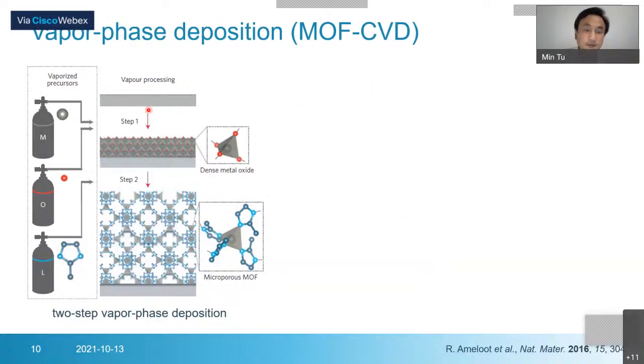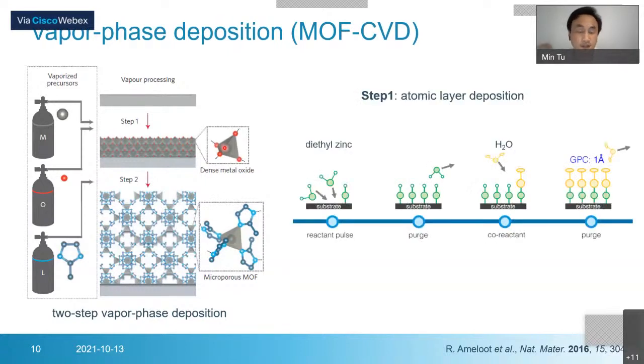The first step is to deposit the metal oxide as a precursor layer. Then we use an organic linker in the vapor phase to react with the precursor layer to get the MOF film. So let me introduce it in a bit more detail. In the first step they use atomic layer deposition. Atomic layer deposition is similar to what I discussed before, the liquid phase layer by layer deposition. Here it is gas phase layer by layer deposition.